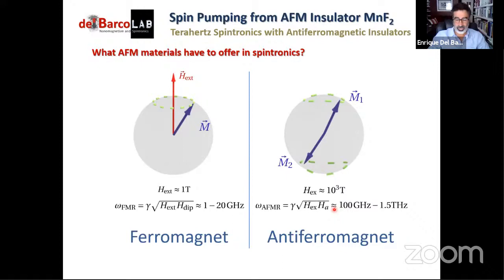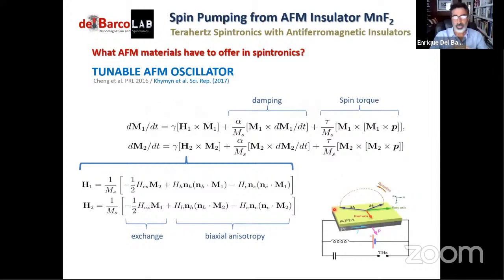Indeed, the frequency of rotation can be tuned by the strength of the perturbation. And there are two theoretical proposals of a terahertz antiferromagnetic oscillator, one by Cheng and collaborators and the other one by Andrei Slavin and collaborators. I'm going to explain one of them, and it's illustrated in this device. So this is an antiferromagnet. It's an easy-plane antiferromagnet, actually a biaxial antiferromagnet with a hard axis. The hard axis is directed parallel to the interface in this direction. The easy plane is perpendicular to the interface between the antiferromagnet and an adjacent heavy metal like platinum.